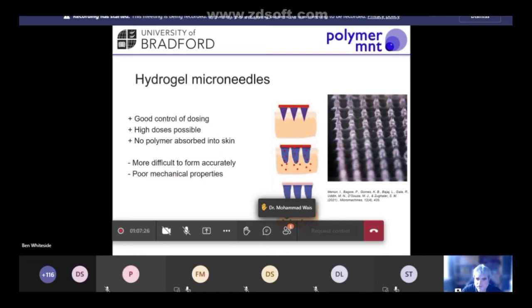So the drug that was effectively trapped in there before in its dried state becomes able to diffuse out of the hydrogel into the local area in the skin. Basically, as soon as that's been activated, the drug can diffuse out. And then once that process has happened, the hydrogel microneedle can be removed from the skin. So the benefits of the hydrogel microneedle are very similar in some ways to the absorbable microneedle devices.